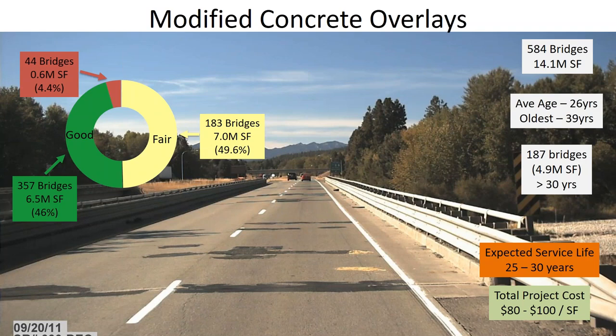So as far as modified concrete overlays as a whole, most of them, over half, are in fair condition. You might see a lot of decks that look like this as you drive across the state. 44 are in poor condition, that means over 2% patching. The oldest is 39, and the average age is 26. So this predominantly is our primary method of rehabilitating concrete bridge decks. We expect a life of 25 to 30 years, with a total project cost of about $80 to $100 a square foot.